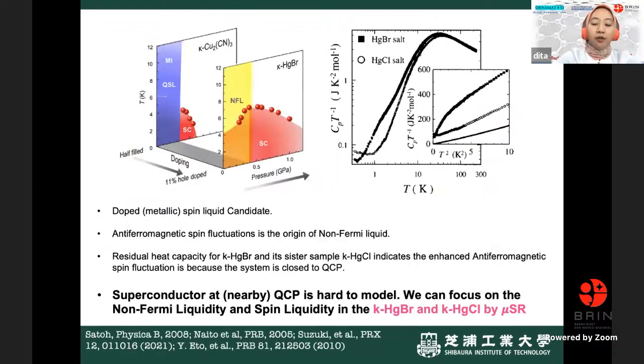Okay, so I start from mercury bromide because it has the triangular lattice as I showed before, and the spin characteristic of this mercury bromide is similar to the other quantum spin liquid system, the organic system. So it's suspicious, maybe this is originally a spin liquid, but due to the doping, it becomes metal and superconductor. So it's a candidate of doped spin liquid. And then at low temperature, probably there are antiferromagnetic spin fluctuations, because this is the origin of the non-Fermi liquidity sensed by the resistivity measurement.